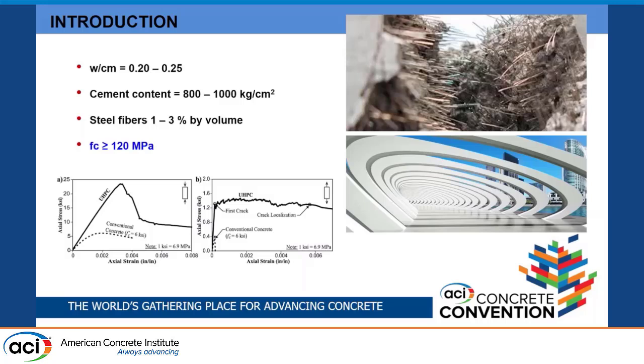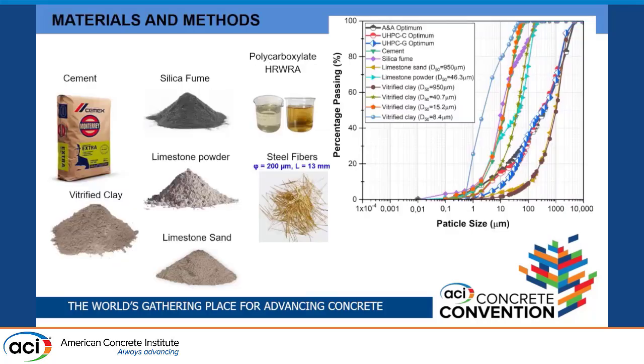And to improve the brittleness of the material, the solution was to incorporate a significant amount of fibers. You can see in the pictures, and you can have an idea of how much fiber that concrete has. It goes from 1% by volume to 3%. In our case, we use just 1%. These concretes are also becoming very popular for architectural applications, as you see in the bottom pictures. The fibers help to give ductility to the concrete, because concrete is a brittle material, not a ductile material. With that amount of fibers, it reaches almost the ductility of steel. Almost.